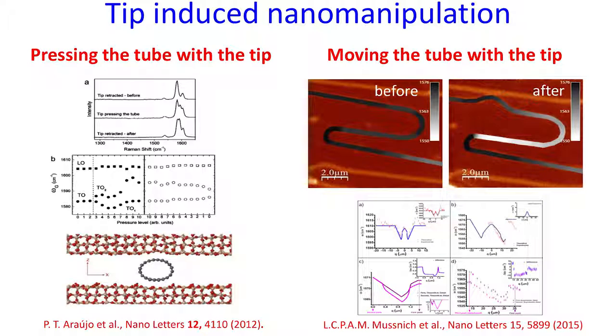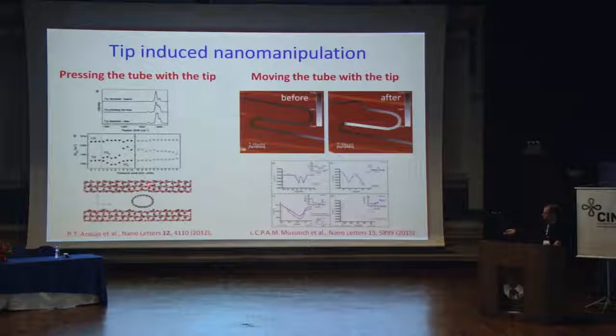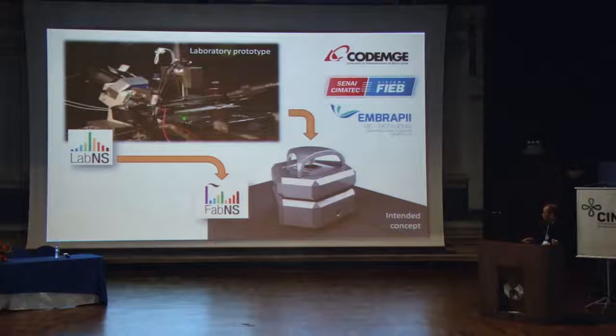you want. So this is one analysis where we had a nanotube, and what we did was we used the tip to press the nanotube and make it oval, okay? And we analyzed the mechanical properties. And here is an example where we land the tip here and push it up, so the nanotube bends like this, and the bending here makes a strain that propagates all over the nanotube, and you measure this from the Raman frequencies, which are related to strain. So with this technique, you can also do this kind of nanomanipulation and probing.